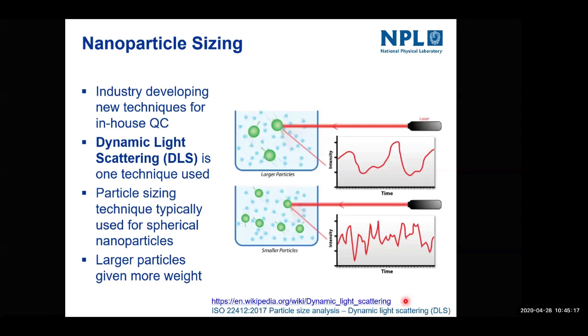Because again, there's another issue with techniques such as this that's around reproducibility and actually repeatability. Even taking the same technique, so the same instrument, the same person, the same sample, you can get a 40% variation in the results. So again, it's something that has to be really taken into account when you're using these techniques for quality control. They're probably good for in-house understanding of your batch-to-batch reproducibility, but not necessarily for quantitative assessment of measurands to then report.